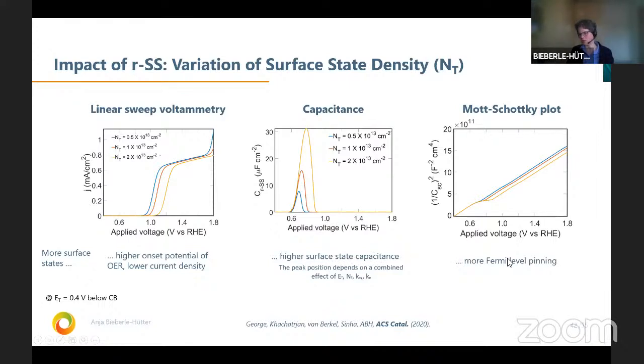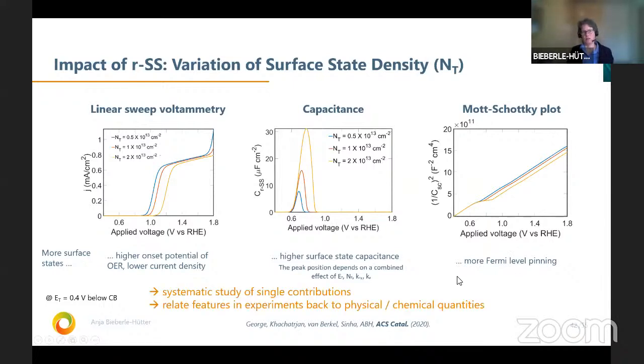And we find also that we get more Fermi level pinning. You can say, yeah, this is what is expected also from experiment, but it's nice to see this with these simulations where we start actually from a microkinetic model with the very rough DFT data as input. So we can do systematic studies on single contributions and then relate this to the physics and the chemistry in the experiment. And as I said, in the experiments, it's much more difficult to change, for example, single parameters.